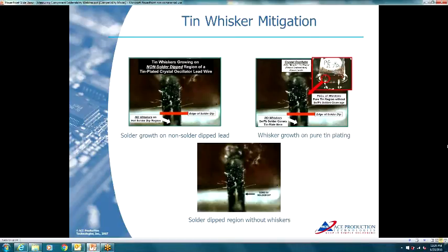Here's some graphic difference on a crystal oscillator. It's a little hard to tell, but if you look at the red horizontal line, these parts were retinned. Below the line is where they were retinned, and you can see no tin whiskers, and you can see tin whisker growth above it where they were not immersed. The pin was not immersed in solder. You can see it a little bit better on the bottom image, that once you solder dip, remove the tin plating and replace it with a homogeneous tin lead plating, you can see there is no growth of tin whiskers.